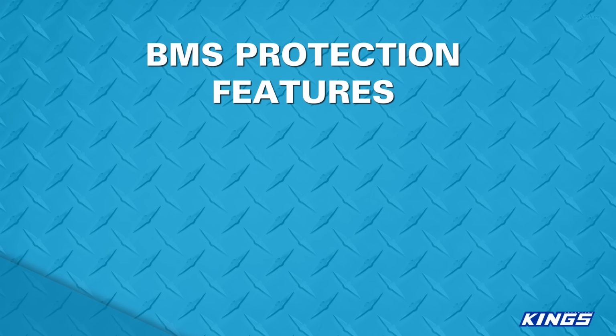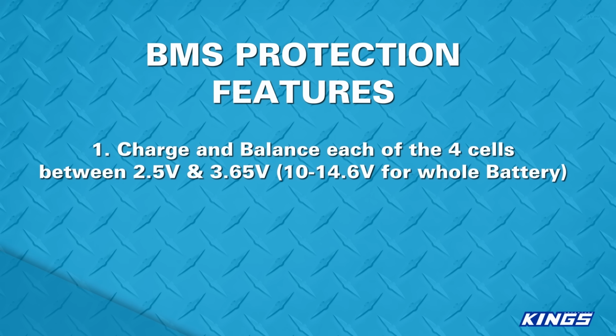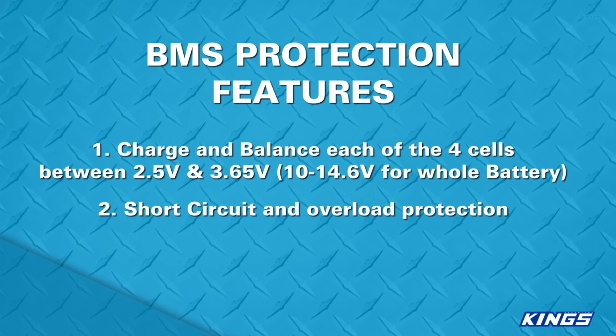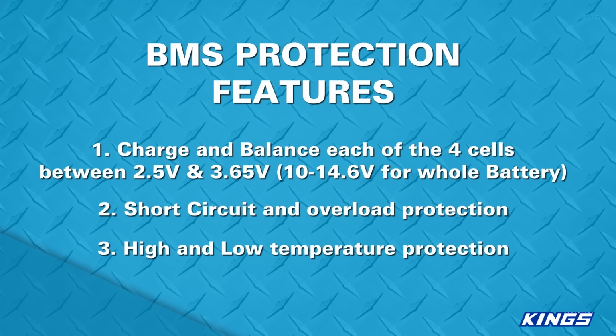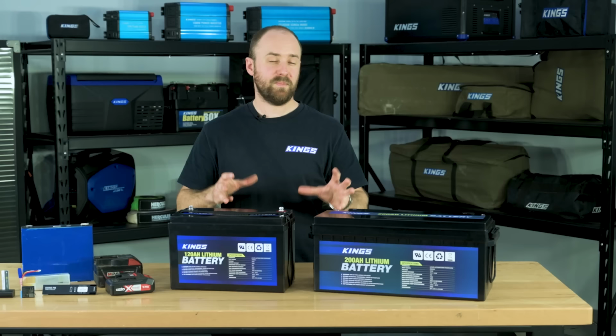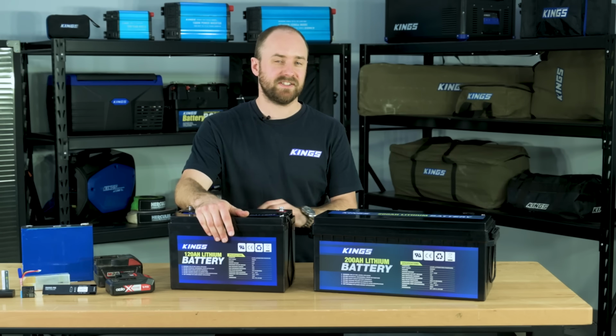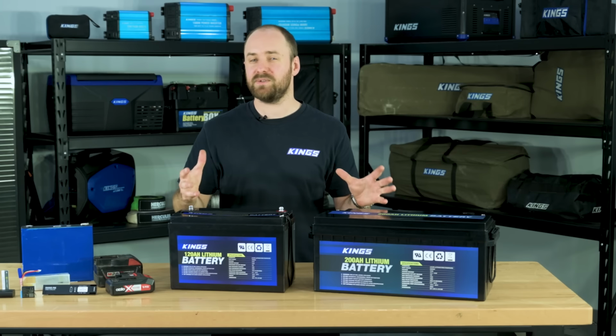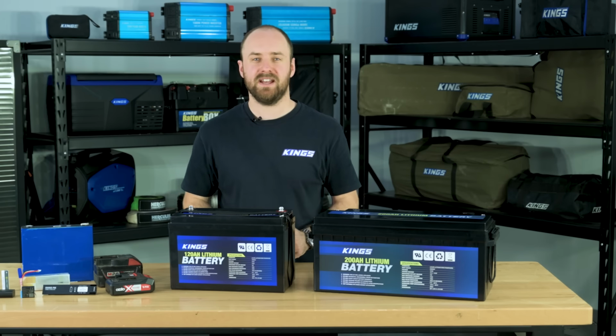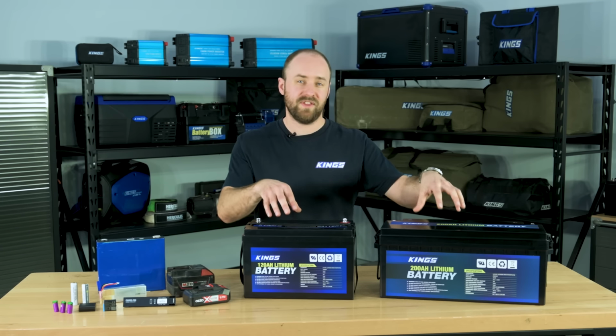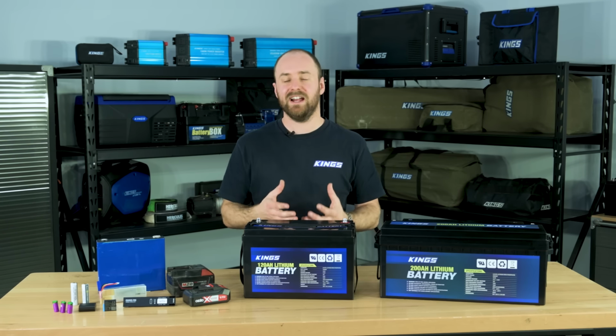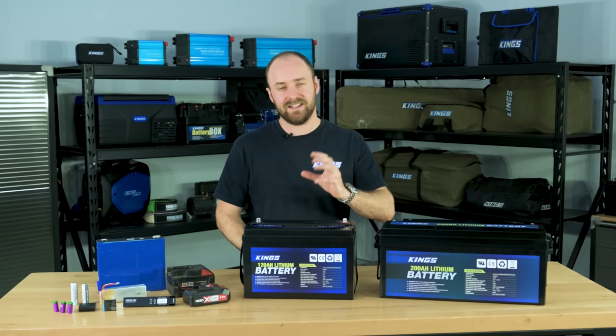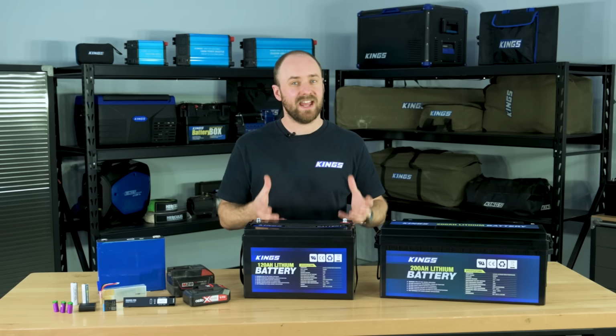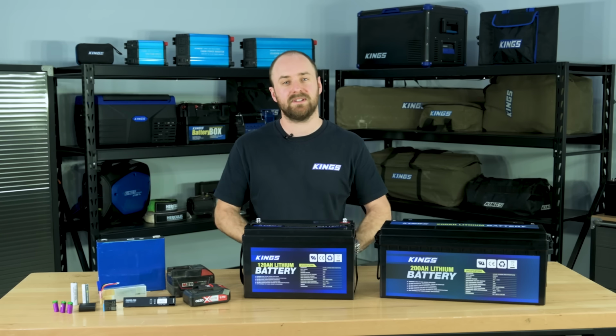Most importantly, the BMS in these batteries will prevent each cell going below 2.5 volts or above 3.65 volts. They also have a short circuit and overload function, plus temperature sensors to prevent the battery from overheating or from charging in cold temperatures. And to ensure the BMS is protected, these battery cases are sealed with an IP65 rating, and the batteries themselves have to pass a vigorous vibration test. The BMS is why you couldn't use one of these lithium iron phosphate batteries to start your vehicle. For that, you'd need a dedicated lithium jump starter. An AGM battery is capable of emergency jump starting a vehicle, so that's something to take into account.